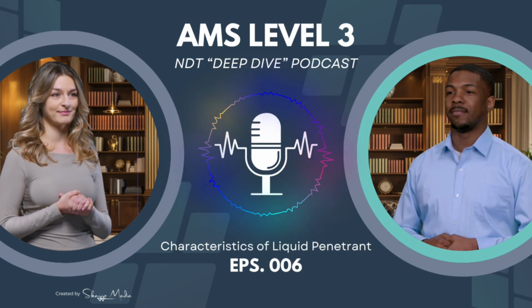Yes. And this law basically tells us that in extremely thin films, like the tiny amount of penetrant seepage from a microscopic crack, the light absorption drops off incredibly fast. Below a certain thickness, the indication just becomes effectively transparent. Our eyes simply can't perceive that faint color. It sets a real physical limit on their sensitivity.